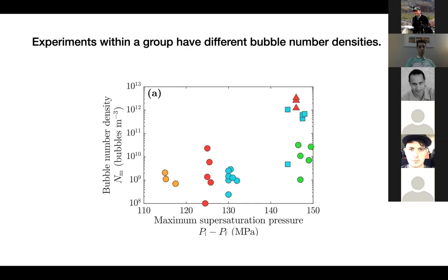Here I'm showing bubble number density observed in our experiments as a function of supersaturation pressure. Different symbols show different groups of experiments. There are overall six groups of experiments. What we see here is that samples within each group of experiments have different bubble number densities. For some experiments, the variation is more than two orders of magnitude.